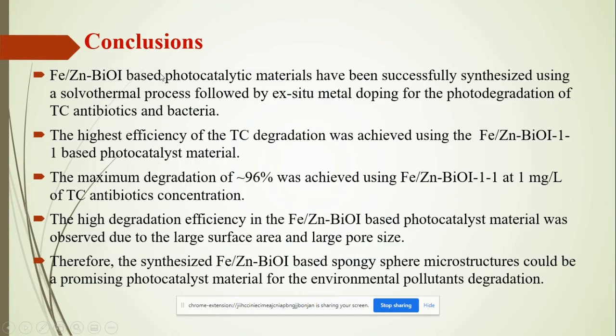In conclusion, we can say that FeZn based BiOI based photocatalyst material has been successfully synthesized using a solvothermal process followed by ex situ metal doping for the photodegradation of TC antibiotic and bacteria. The highest efficiency of TC degradation was achieved using FeZn and BiOI 1:1 based photocatalyst material. The maximum degradation of 96% was achieved using FeZn and BiOI at 1 milligram of TC antibiotic concentration. The high degradation efficiency was observed due to the large surface area and large pore volume. Therefore, the synthesized FeZn and bismuth oxyiodide based spongy microsphere could be a promising photocatalyst material for environmental pollutant degradation.